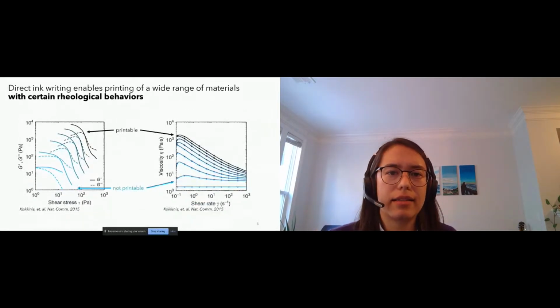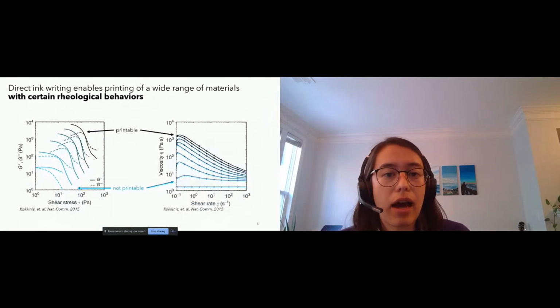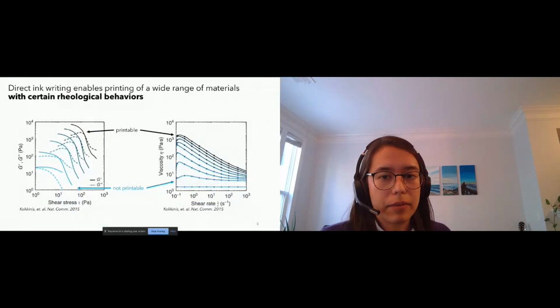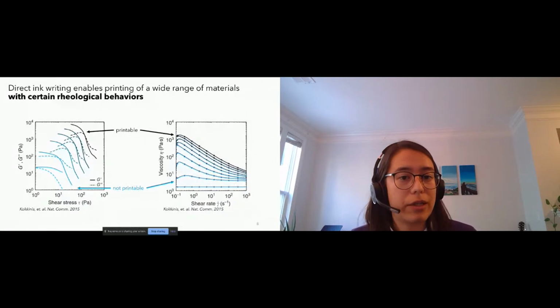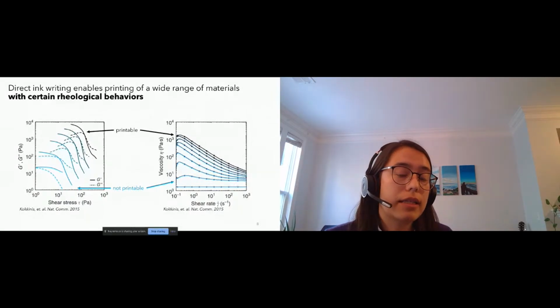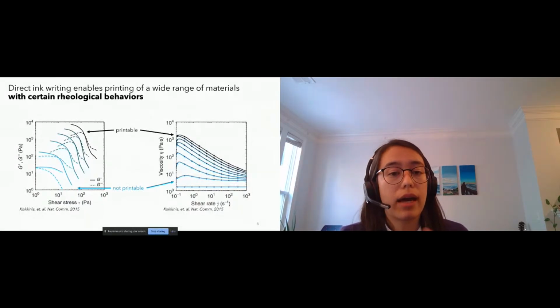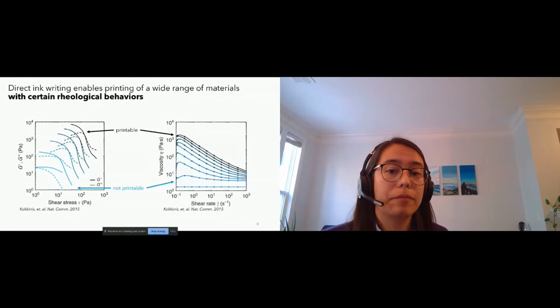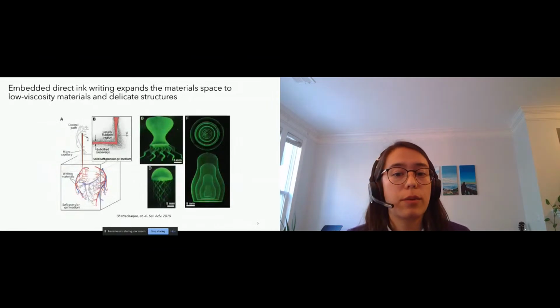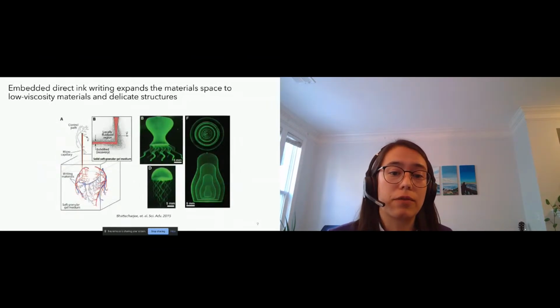So among these inks that are plotted here, at the top of the plot where we have these dark lines, those inks are going to be printable because they have a high enough yield stress that they will not just collapse under their own weight. However, at the low end of this plot, these light blue inks are not viscous enough, not shear thinning enough, and don't have a high enough yield stress to be printable using direct ink writing. So that's where embedded 3D printing really becomes useful.